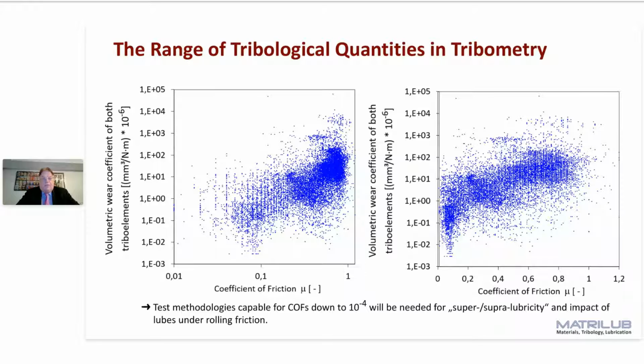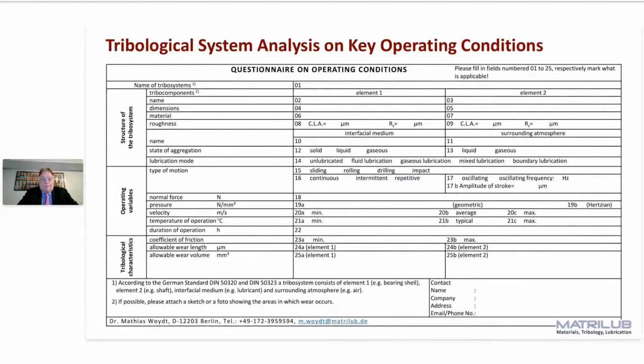Those databases also have a very important capability, because when you now measure a material, a coating, a lubricant, and you get a wear and friction result, is this good or bad? When you have such a database, you put in the new results and you see exactly where you are sitting in comparison to all other past test results.